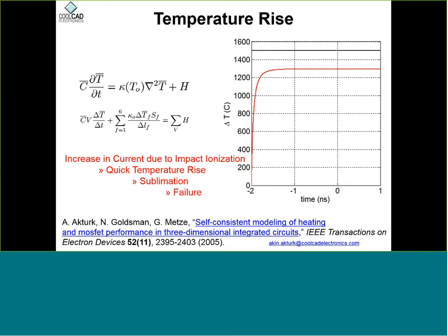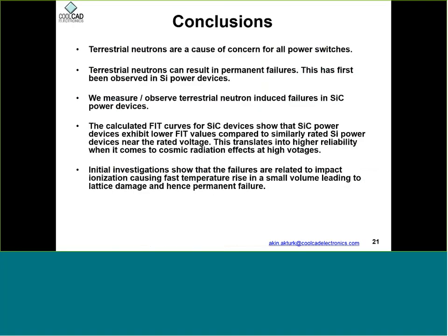Okay. So in summary, you have neutron-induced knock-ons causing current flow in a high field, and you have Joule-type heating in a very small volume, leading to a failure. But to conclude the talk, we went over what's causing terrestrial neutrons. There are no neutrons in space. They are caused by high-energy protons hitting gases in the atmosphere, and that causes a shower of events. Since neutrons don't have charge, they can travel down to sea level, and there are an appreciable number of neutrons at sea level that can cause the power switch to fail.